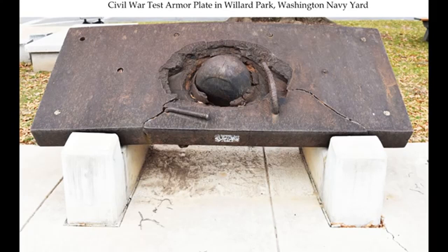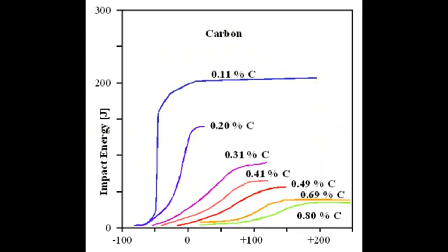There were also further complications with ships' hulls cracking under the stress of oceanic operations instead of flexing as was intended, but that's a completely different story. There was one other factor that was playing into all of this, and that was the presence of trace elements or impurities in the iron. As you can see, these change the duration and location of the brittle to ductile transition point on the scale of temperature, as well as making a difference to the overall resistance of the iron.